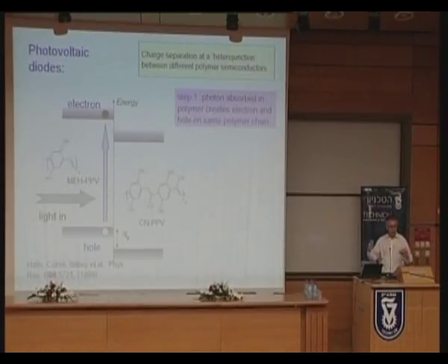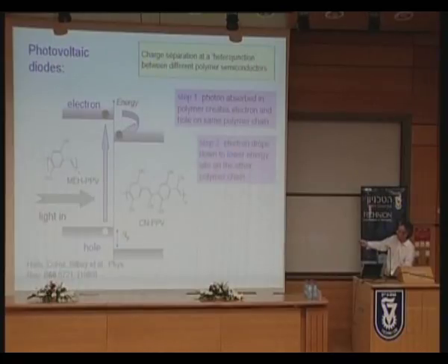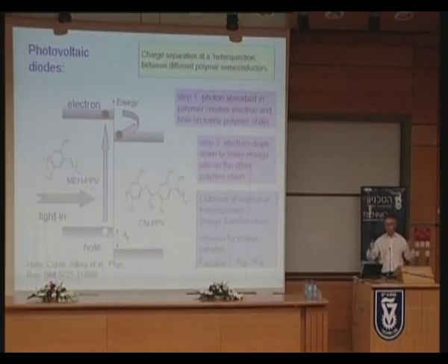And if that's all that would happen, it would remain as a bound state and re-radiate. But if this molecular excitation, the exciton, can bump into the heterojunction, then there's a possibility that it will transfer an electron from left to right, because there's a lower lying energy state unfilled on the right, and the hole left behind won't want to move too. So that's the process of getting charge separation, and the criterion for that to happen is that the offset of these band edge positions is larger than the Coulomb binding of electron and hole when the excitation is just sitting on one polymer chain or one molecule. And the criterion comes out at about half an electron volt energy difference. And it is possible to tune materials. This is a system which obviously works, so that we can get efficient charge separation.